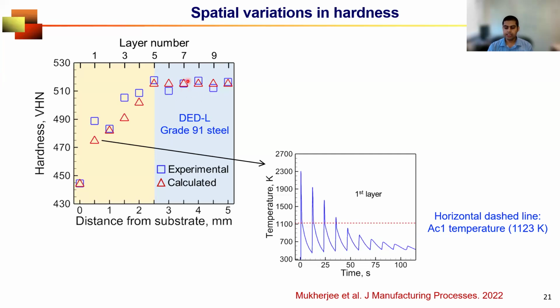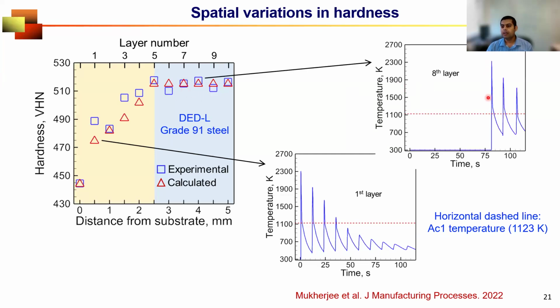What's happening in the top region? The peak temperature never goes below the AC1 temperature. So the martensite that forms here will transform again back to austenite. So this martensite will never transform into tempered martensite. That's why the hardness in this region is controlled by the absolute amount of martensite, not tempered martensite. Okay, so a very complex metallurgical phenomenon we are trying to capture by using this kind of process model.